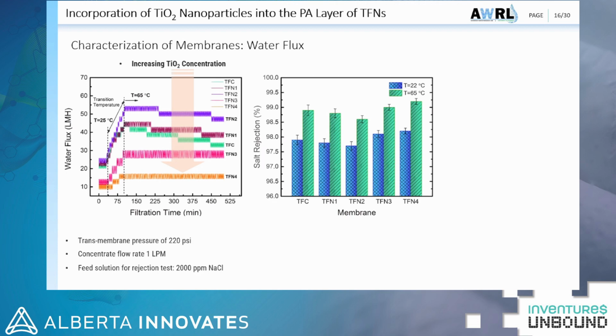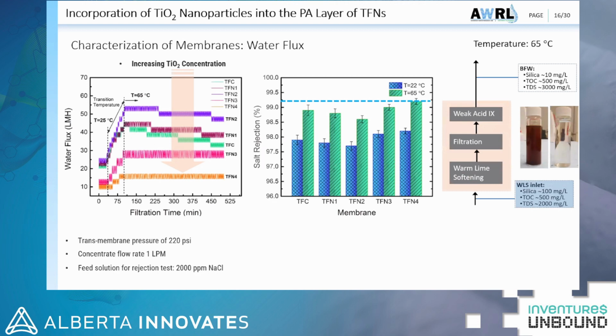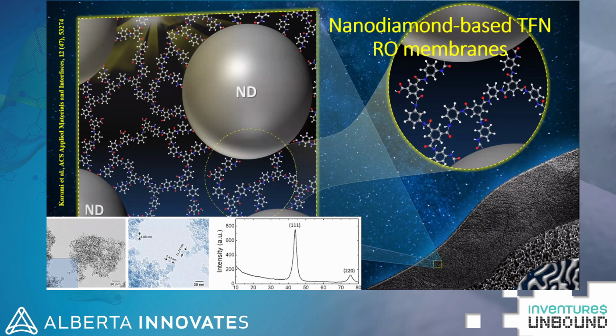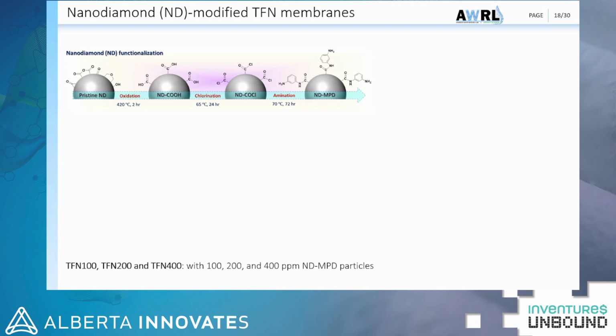These membranes were also used for WLS feed water treatment at 65 degrees C, and the performance did not decrease over time; it was stable at 65 degrees C. In a recent effort, we added functionalized nanodiamond to the top polyamide layer to improve the thermal stability. The TEM and XRD characterization of nanodiamonds showed synthesis of very small size and well-dispersed nanodiamonds. In this study, to increase the compatibility of the nanodiamonds with the polyamide matrix and decrease the chance of aggregation, the surface of the nanodiamonds was functionalized with MPD molecules.